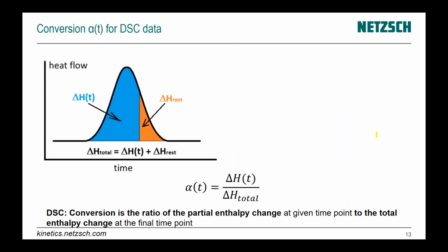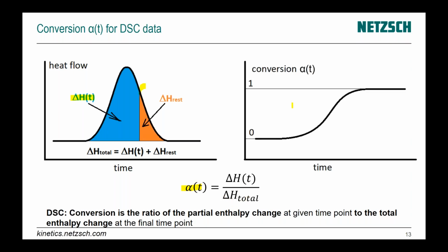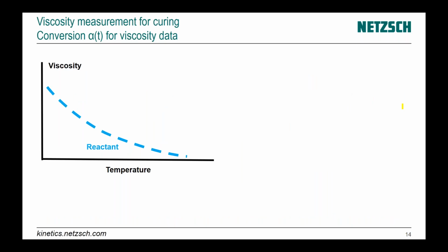So degree of conversion shows what part of reaction is already finished. If we speak about DSC, then again we make a ratio between the current area until the current point to the total area of the peak. And then again we have a value from 0 to 1. 0 reaction is still not started, 1 it is already finished.